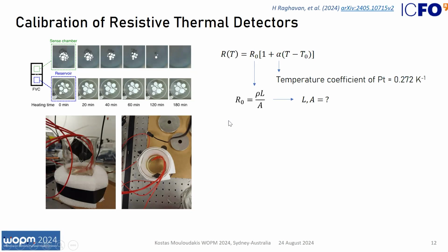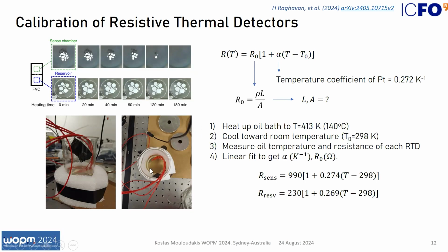So we immersed the whole vapor cell in an oil bath together with a K-type thermocouple, and we heated up the oil bath using a heat plate at 140 degrees, and then we let the oil cool towards room temperature. While doing so, we are continuously monitoring both the resistance of the RTDs and the temperature of the bath. Then using this formula, we fit the data, and we can find R0 and alpha. And alpha was very close to the values we can find in the literature regarding the temperature coefficient of platinum, and therefore we believe that this calibration is valid.